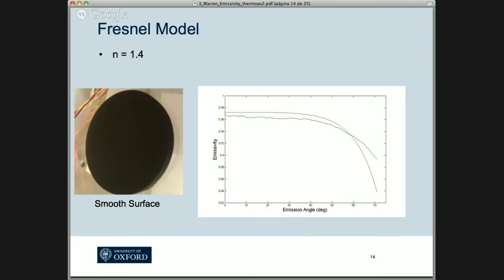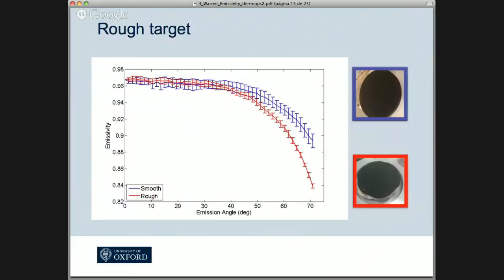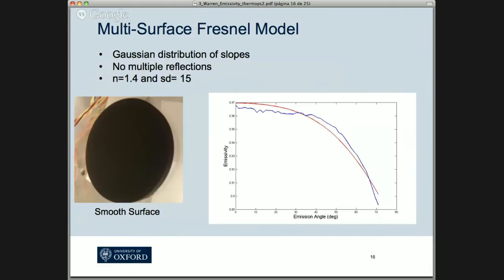So this blue line is the target I was just showing. Red line is another target I made, which has much more texture to it. And you can see again, these 2 have a very different function from 45 degrees onward. It looks like surface roughness has a large impact. So I then tried to take into account this roughness in modeling to try and improve my modeling. And I was using this multi-surface Fresnel model, which basically just takes a set of slopes and then weights the contribution from each slope using a Gaussian distribution. And as you can see, it improves things, but it still wasn't a great fit.